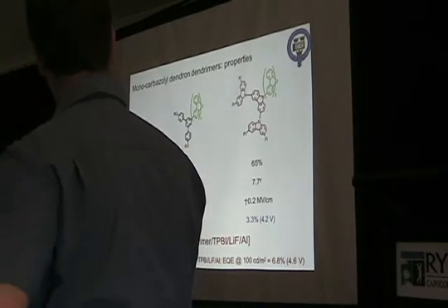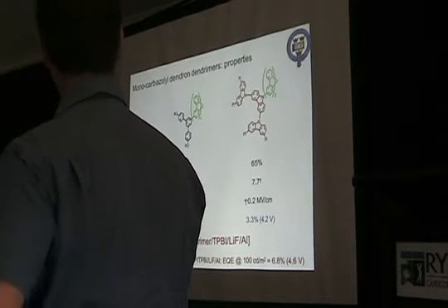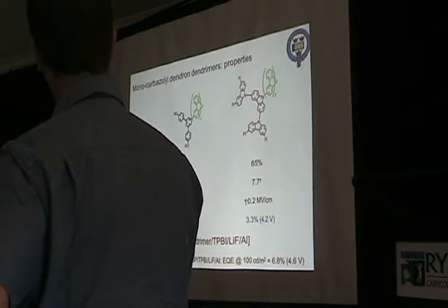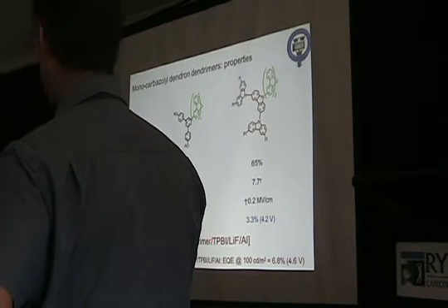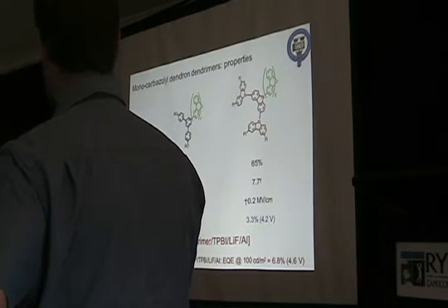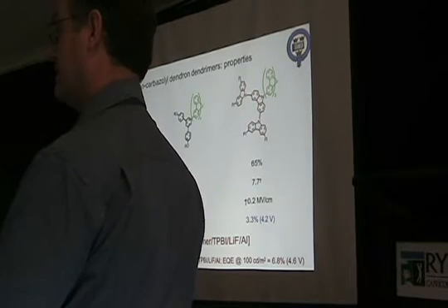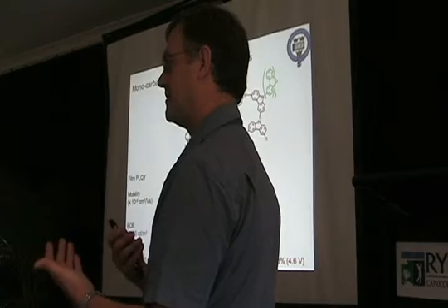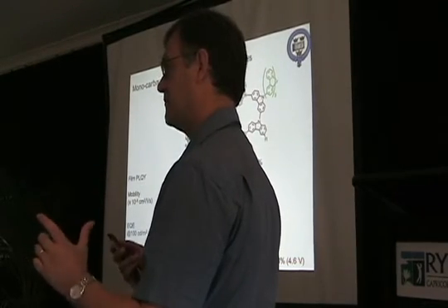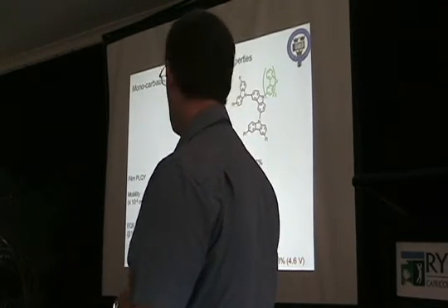This material transports electrons and blocks holes. If the holes all race across and hit there, then all the excitons are formed at that interface, and there are other quenching processes that go on, because it's a phosphorescent system, which means the lifetime is fairly long.